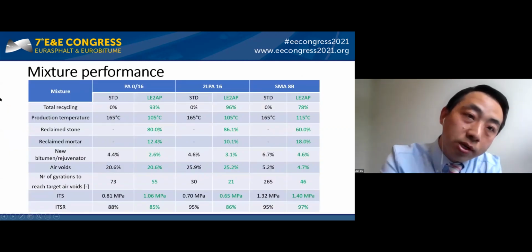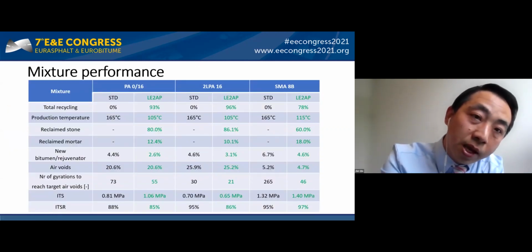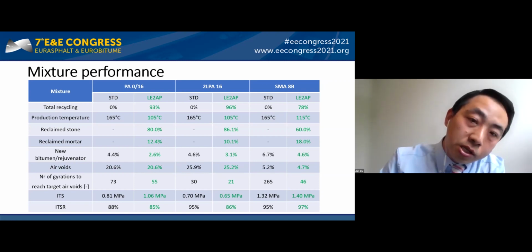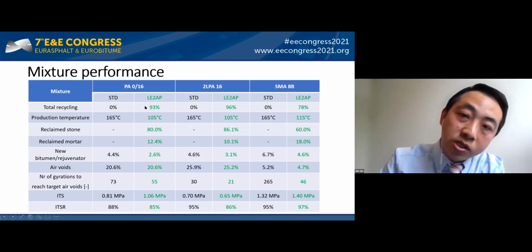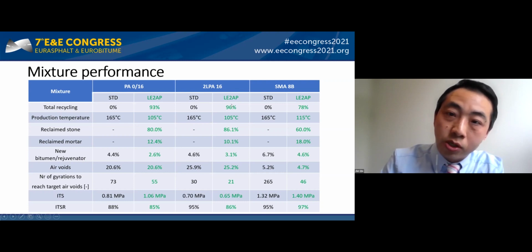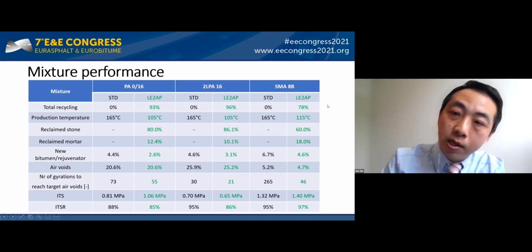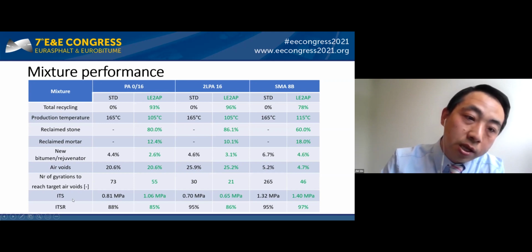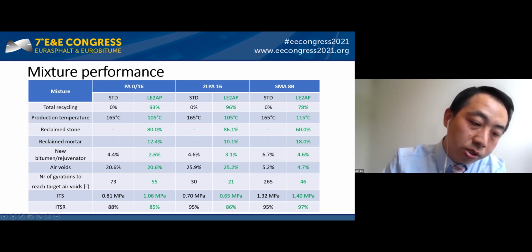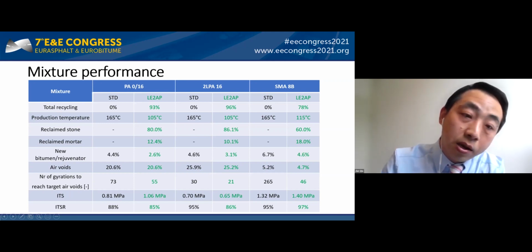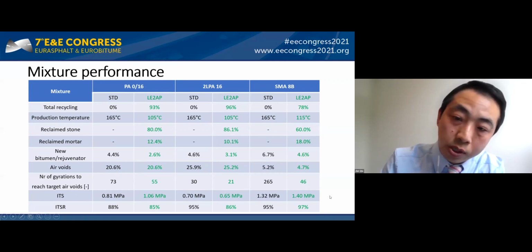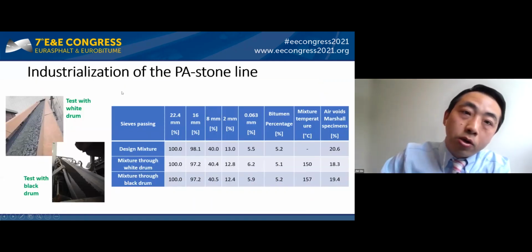When you have the mortar produced, you can then produce the mixture. You will see that with the 3 types of mixtures in the LE2AP category, there is a very high percentage of recycling and low production temperature. In the end, you will see that their strengths and water sensitivity values have very good results. Now we go a step further.